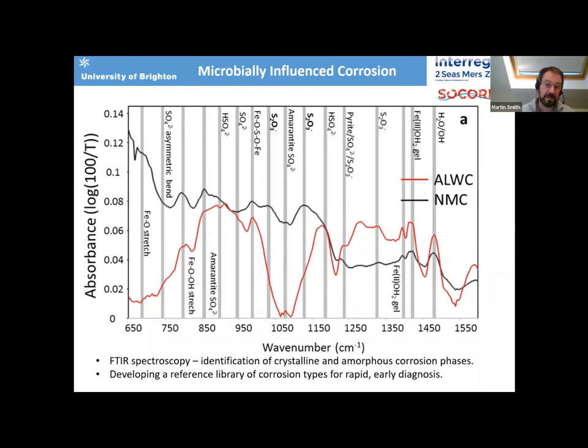When we look at the infrared spectra of these things, so this is wave number against absorbance, we see the sulfate minerals, but we also see a lot of evidence of intermediate oxidation state sulfur compounds. So here we've got infrared absorbance for iron oxides, iron oxyhydroxides, but also sulfates, which we already know are there, but also thiosulfate. So we're not just seeing sulfate minerals and sulfide minerals, we're seeing the intermediate oxidation states are present as well. And this becomes really important when we start to understand the mechanism of what's going on.